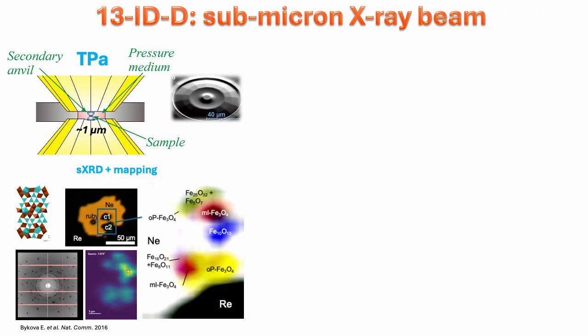As I have mentioned, to take full advantage of the APS upgraded beam, we are upgrading our beamline station. One of the reasons is that when we do experiments at terapascal pressure, we use a double stage anvil, and the sample size is around 1 micron. After laser heating, we have multiple phases. As you can see here, it's only 50 micron, and when we zoom in, we see multiple phases.